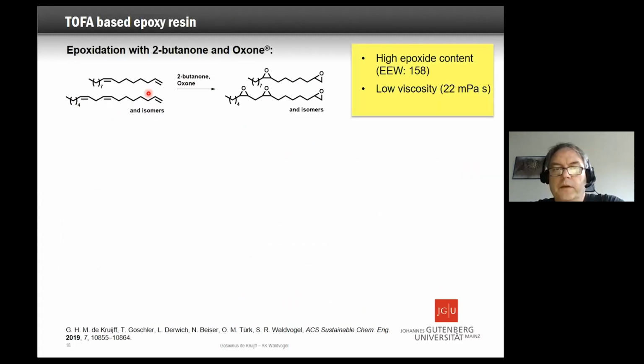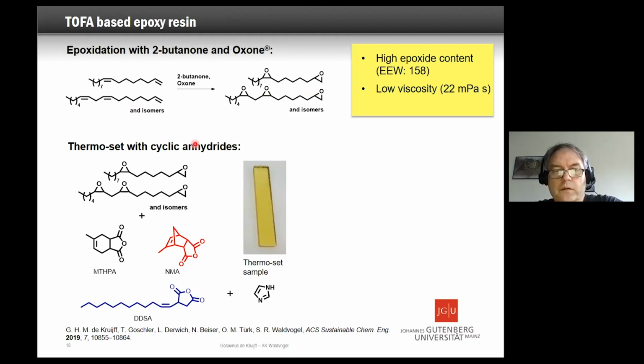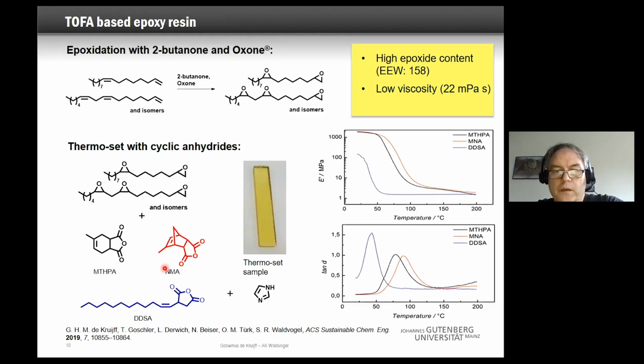We were able, after epoxidation, which we used here just a ketone and oxone to get the epoxy derivatives out of it. And you can make thermosets out of it, and you will see, as expected, especially this system and this system gave a more stable thermal system, and you can use that compared to other systems which are out there.